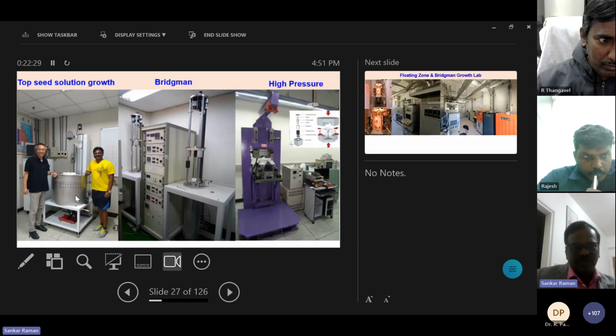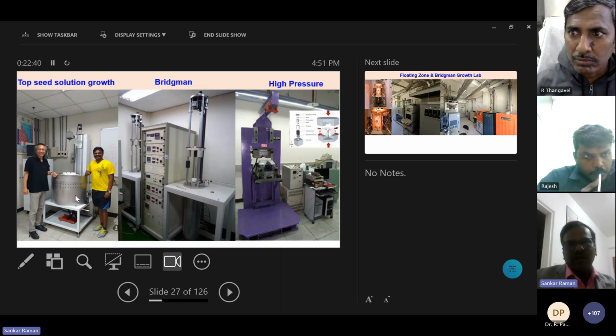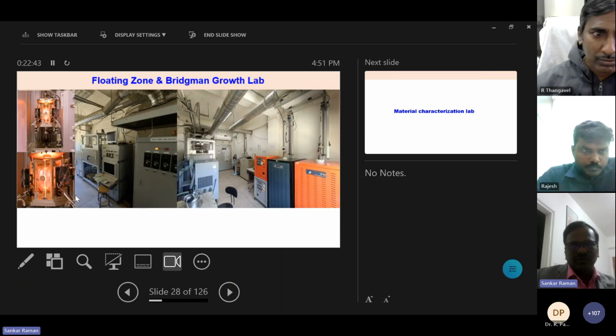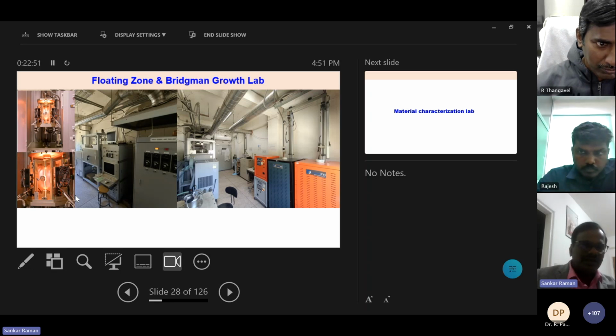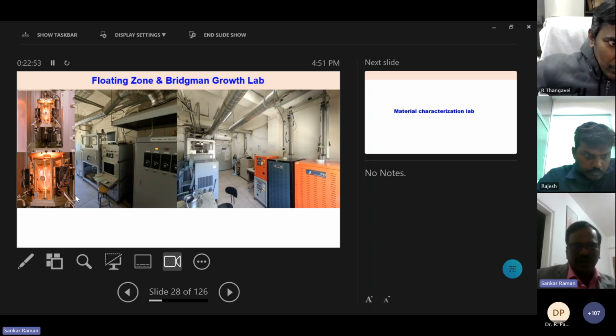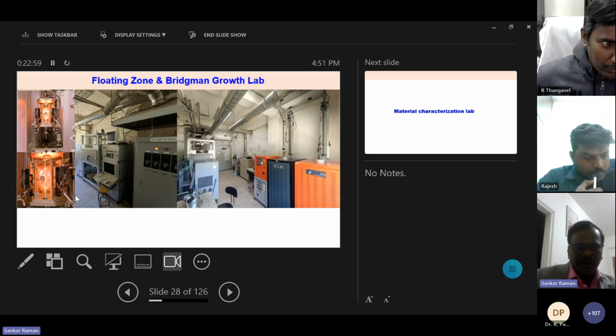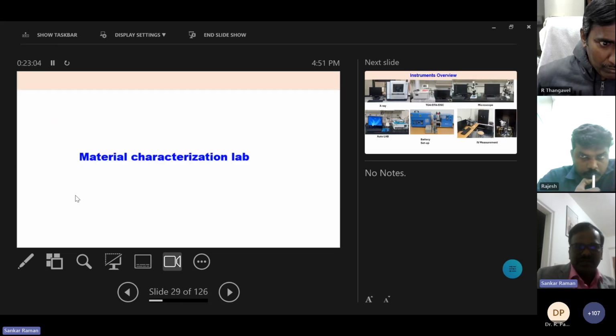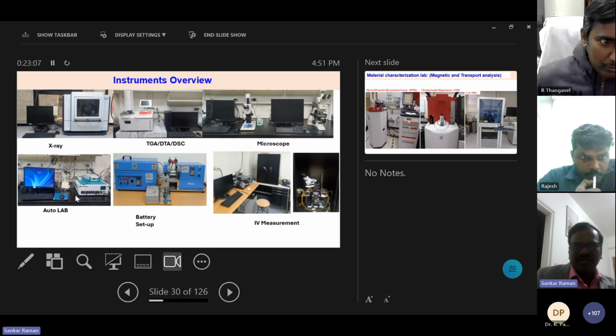This is top-seeded solution growth, Bridgman. High pressure, we can go up to 8 GPa. We can grow some of the metastable materials, which are sometimes unstable and can only be grown under high pressure. And also we have a Japanese lamp floating zone furnace. We can grow any kind of congruent melting material above 3,500 or 4,000 degrees. Using this floating zone furnace, we can grow all kinds of oxide materials, including metallic or alloy-based materials also. Then we have a separate material characterization lab with X-ray, TGA-DTA.